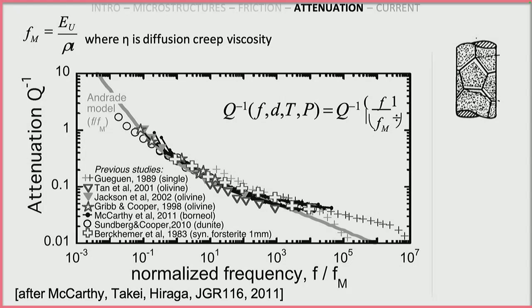And we were looking at a variety of temperatures and grain sizes, and we figured out how that scaled to each other. And so then we started taking all of the other data sets of olivine, single crystals, large crystals, mixed rocks, and we figured out if we scale them by the Maxwell frequency, which is the unrelaxed modulus divided by the viscosity.